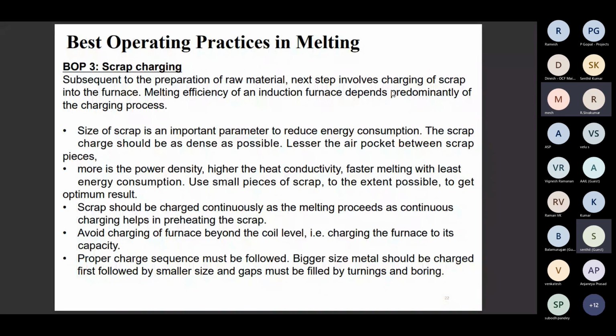Scrap charging. Subsequent to the preparation of raw material, the next step involves charging the scrap into the furnace. The size of the scrap is an important parameter to reduce energy consumption. The scrap charge should be as dense as possible, with fewer air pockets between the scrap pieces, so that induction takes place uniformly. The melt rate is then high and the melting time is reduced. Otherwise, improper size of scrap takes extra time, so energy is unnecessarily wasted. And the higher the power density and heat conductivity, the faster the melting with the least energy consumption.